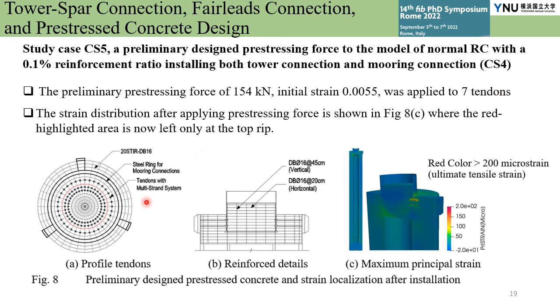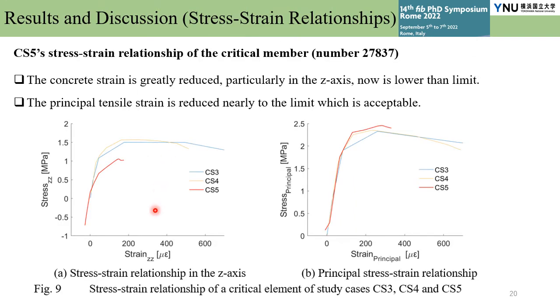Utilizing a multi-strand anchoring system, as shown in figure A, the strain distribution after applying prestressing force is shown in Figure C, where the red highlighted area is now left only at the top rip. Case 5 stress-strain relationship in z-axis and the maximum principal stress-strain relationship of the critical member are plotted together with Case 3 and Case 4. The analysis results show that the concrete strain is greatly reduced, particularly in z-axis, with the concrete walls pre-compressed by pre-stressed tendons. The strain is now lower than the ultimate tensile strain. The principal tensile strain is also reduced nearly to the limit, which is acceptable.